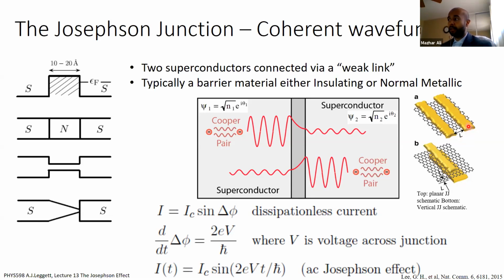Now, it's hard to tunnel Cooper pairs across a good insulator for 80 nanometers. It should just die. The wave function should basically decay completely before it reaches the other side, as our picture shows. So this is much more commonly seen with metallic barriers, or in very specific types of fabrication, the famous aluminum oxide aluminum junction, but that's made in a special way. So it's able to make a very short channel that is not otherwise easily achievable.